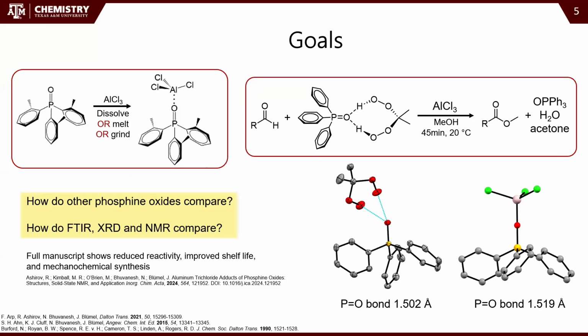So you can see with the X-ray diffraction, the bond length of the phosphine oxide bond, the PO bond, is longer with the aluminum chloride adducts, and that's indicating that it's a stronger adduct ring. So we wanted to look into these aluminum chloride adducts and characterize them so that we could start to probe what role those play in this direct esterification reaction.